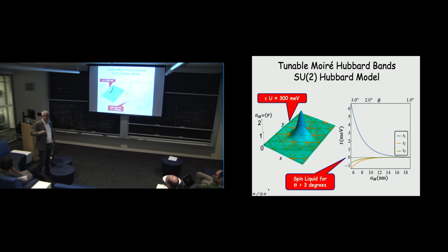And that means, because the lattice constant is humongous, that the number of electrons you need to add to fill a band is much smaller. In fact, you can completely occupy and empty these bands with gates. So you can explore any band filling without changing the chemistry at all, without any chemical doping.